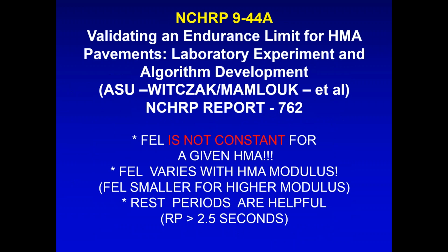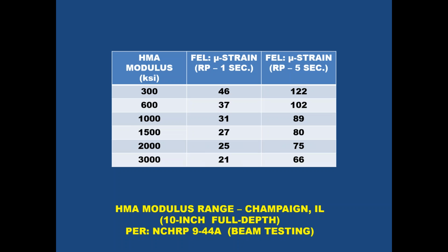Here's what they found. Fatigue endurance limit is not constant for a given HMA. There's no such thing as a given value. It varies with modulus. You get a smaller fatigue endurance limit for high modulus materials. Throw in a rest period. In other words, instead of going bump, bump, bump, bump, provide a little rest between load reps, and you'll find that the fatigue life increases. This shows that effect.